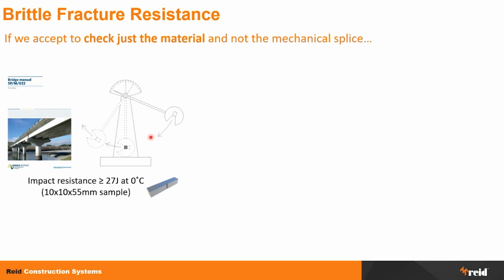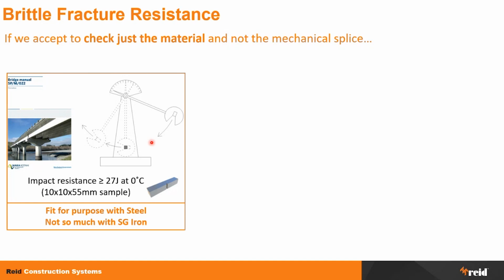And the thing is that this is a test, first of all, on the material, not on the actual element, and also not on the actual connection. So we don't know what happens inside the threads and all the rest, particularly when there is a system, which is not the case for our system, where the thread needs to be cut from the bar with some cold forging or something like that, that might compromise the ductility. And so this is a test which is suitable for steel, but is not actually fit for purpose for spheroidal graphite iron because of its nodular composition.